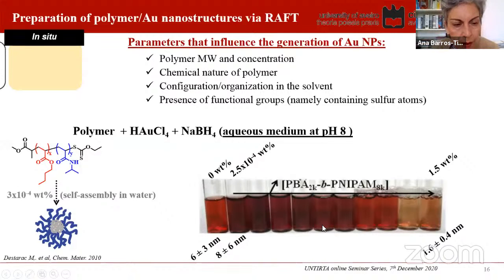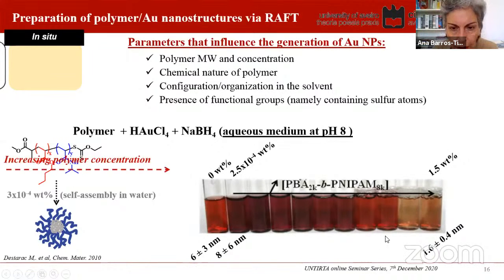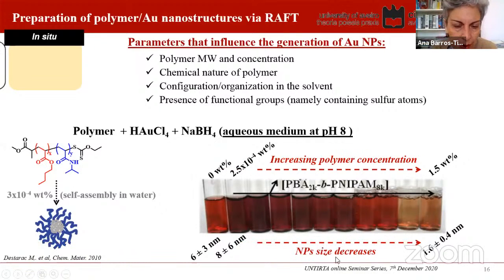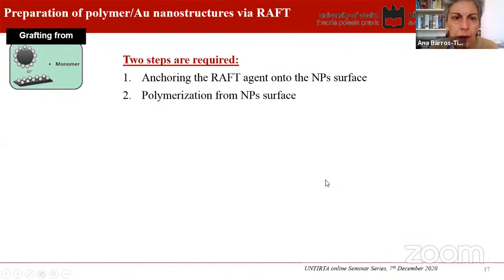using different polymers, namely Destarac had reported a very detailed amount of work using a very distinct type of polymer, but realized that as the concentration varied, the size of the particles would definitely be an issue. So increasing the polymer concentration, the size of the particle decreased, and of course the optical properties would be distinct.